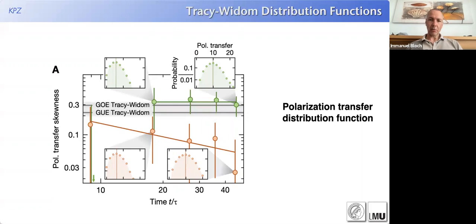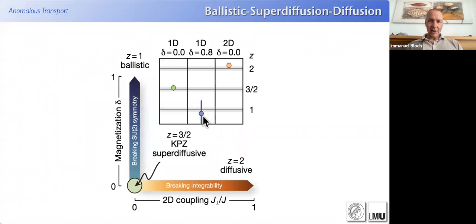So here I just summarize these final results before concluding. On this non-equilibrium dynamics, we see that in the Heisenberg model at very high temperatures, we indeed see super diffusive transport with a dynamical exponent of 3/2. If we break SU(2) symmetry, we go to ballistic transport. If we break integrability, we go to diffusive transport with a dynamical exponent of 2. So we can really uncover all those different transport regimes, and especially this very new transport regime of KPZ type super diffusive transport in the Heisenberg model.